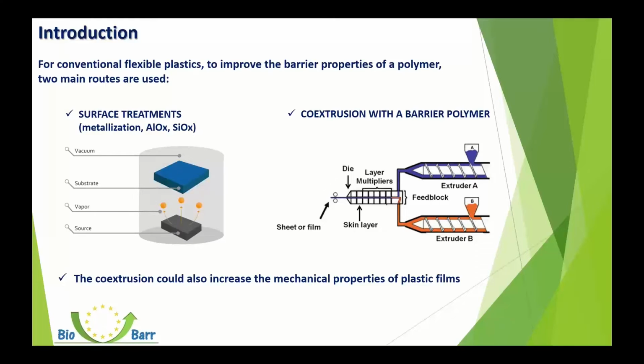Another route to improve the barrier properties of a polymer is the co-extrusion with a barrier polymer. In the step of extrusion of the film, a co-extrusion can be achieved with a barrier layer, that can be applied as core or external layer to the film, like for example happens for polyethylene that is co-extruded with EVOH in order to improve its barrier properties to oxygen. The co-extrusion could also increase the mechanical properties of a plastic film, but also give to it some further properties, like for example sealability, or for example tailoring its coefficient of friction.